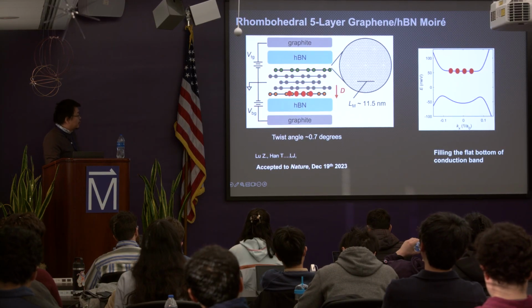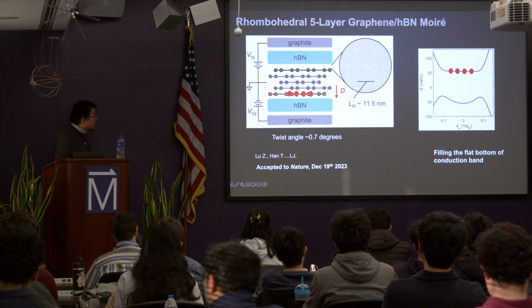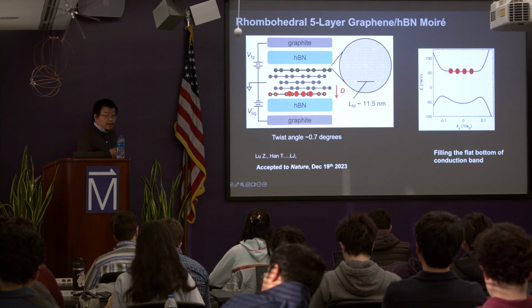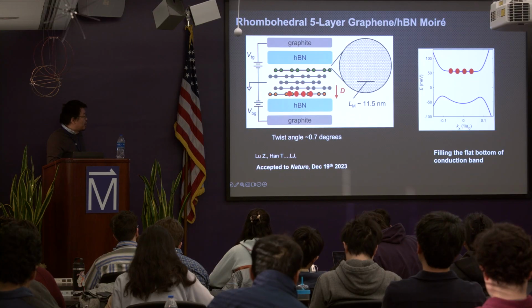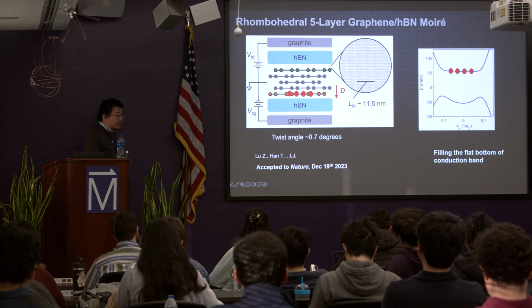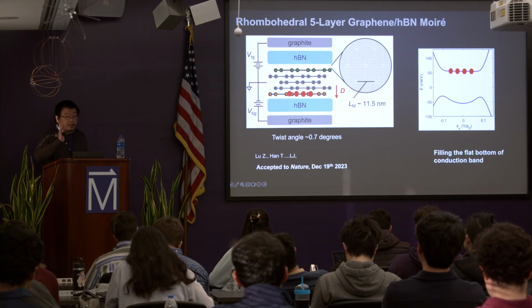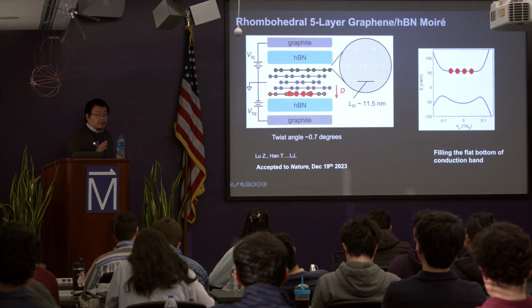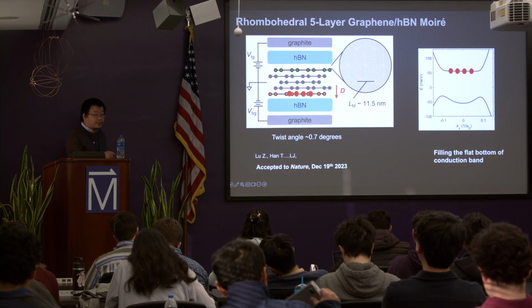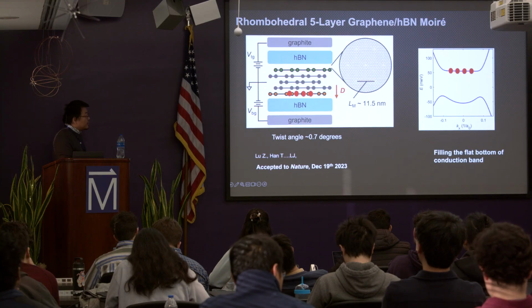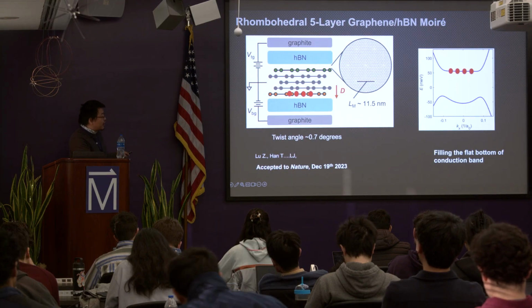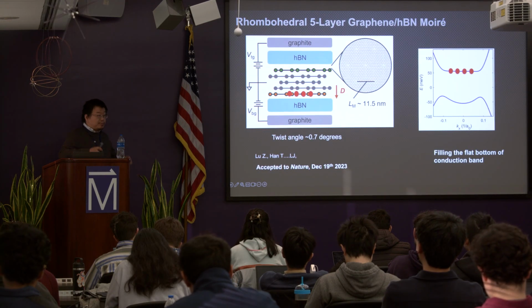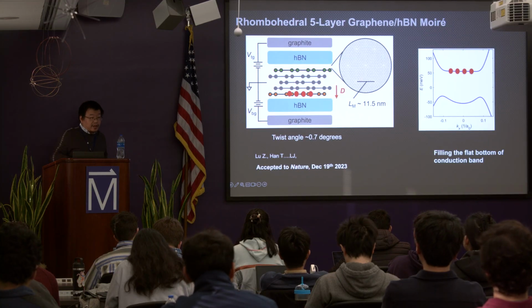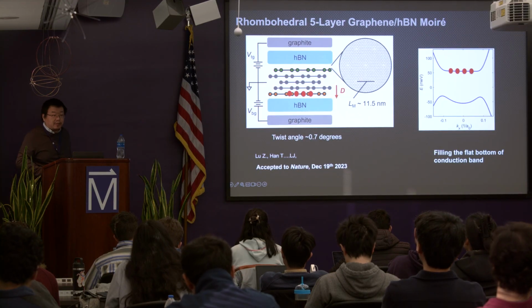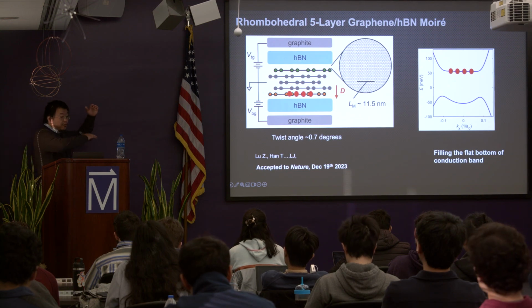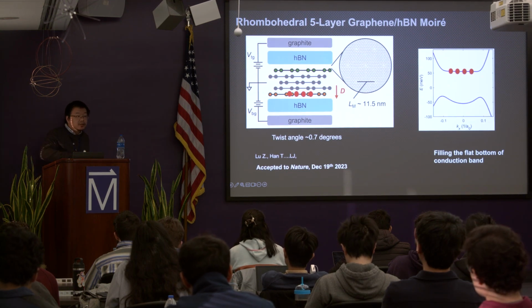So it's forming on the top, sorry. And then you can apply an electric field to open up the band gap. When you're applying an electric field, you're actually pushing your electrons towards one side of the device, right? Because it has finite thickness. So in this case, we have the moire potential on top, and all the electrons are pushed to the bottom. I'm probably going to repeat this multiple times: the moire potential is on the far away side of the electron.